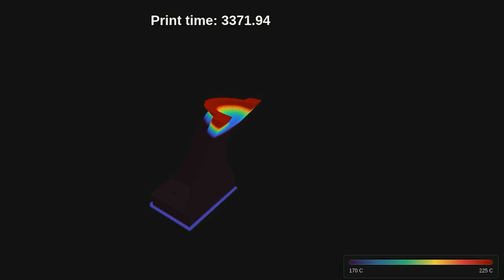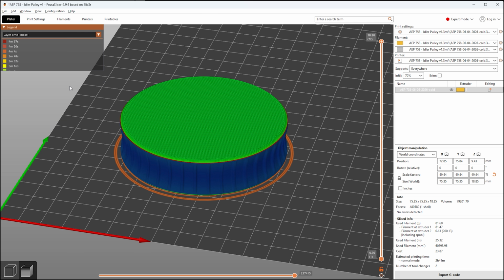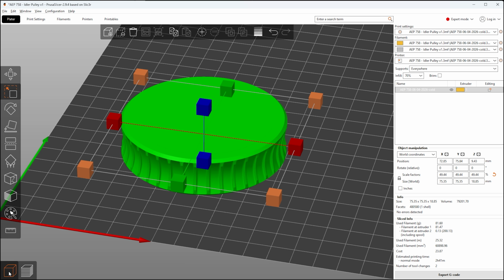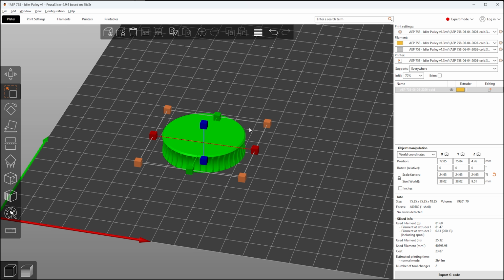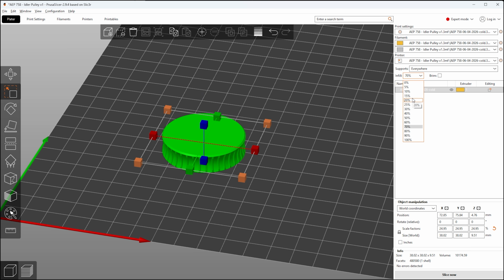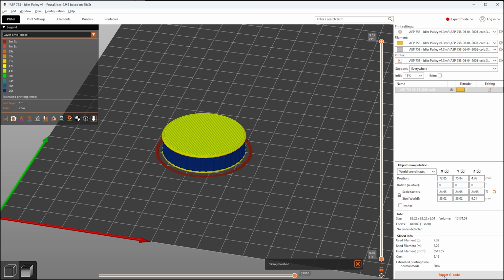In short, those modifications fall into two primary buckets: keeping your layers warm enough for long enough to form strong interlayer welds, and managing stress concentrations as the part cools during the build. The first challenge is keeping each deposited layer hot enough for long enough. When printing in a 120C chamber, this is done by reducing layer times. So printing very small parts, printing thin walled parts, reducing infill, or printing low profile parts that stay within the bed's thermal threshold. Unfortunately, there's no silver bullet here.